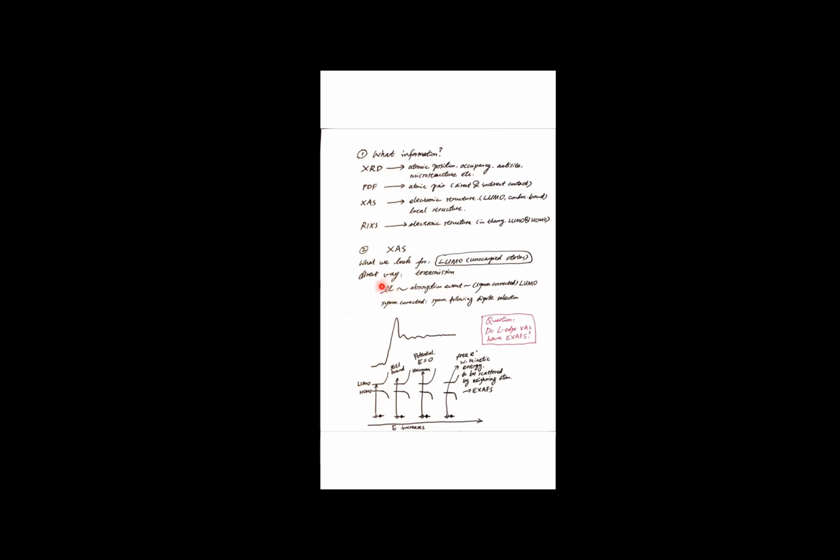But still, if the X-ray goes through the sample, we still have the Beer-Lambert law to follow. Just that in that equation, now this coefficient is pretty large, right? So we do have this kind of correlation, and the number of absorption events can be correlated to the LUMO or the conduction band information, right? Because if we have more unoccupied states, then we can have more absorption events happen. So that's basically a description of that.